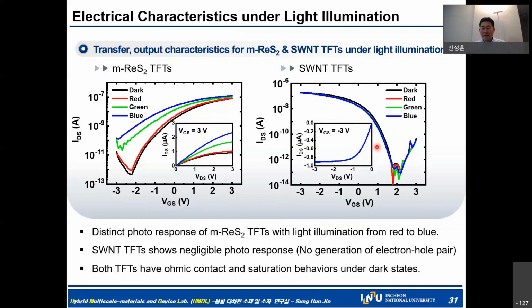That comes from the tight binding mechanism, because the high binding energy leads only to the generation of excitons. It does not lead to the making of free electrons and holes, and that is the reason why we haven't got any photodetectivity for the carbon nanotubes. So in this sense, we have very high sensitivity in the m-ReS2 N-type branch, and by using the carbon nanotube we can achieve the P-type, so N-type and P-type complementary circuits can be easily achieved.